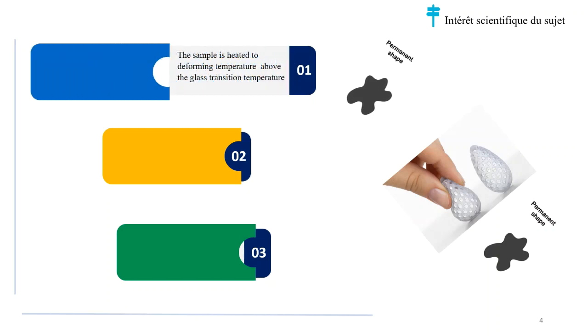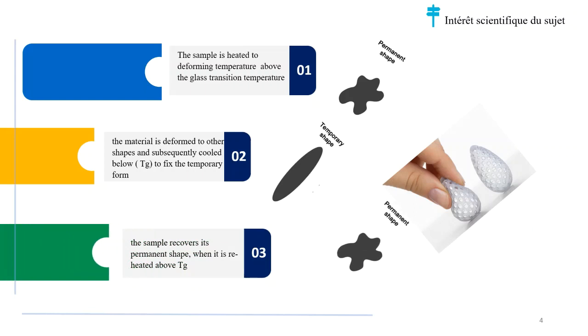Generally, thermally activated shape memory polymers are the most reported shape memory materials. This class can be characterized by a thermomechanical cycle, which consists of 3 steps. The first step is the shape programming, in which the sample is heated to a deforming temperature above the glass transition temperature Tg in order to become flexible and easy to deform. Then the material is deformed to other shapes and cooled below Tg to fix the temporary form. And finally, in the recovery step, the sample recovers its permanent shape when it is heated above Tg.